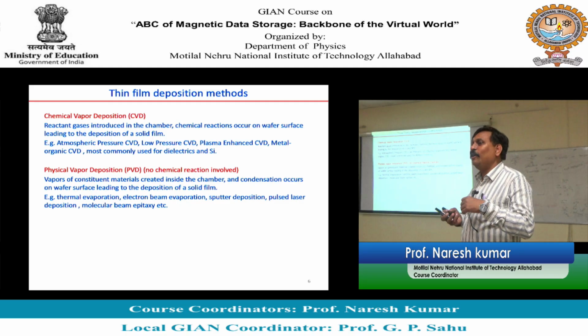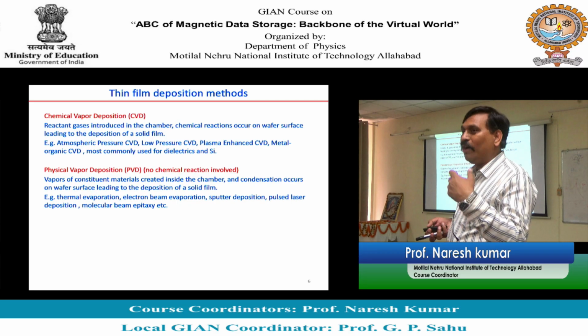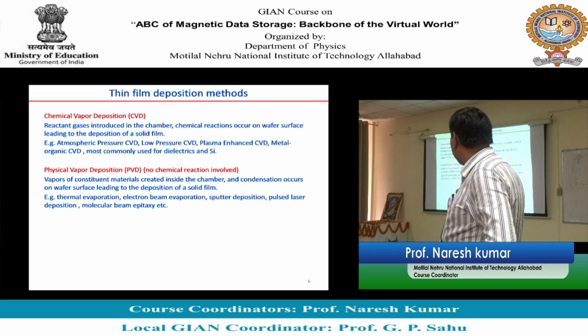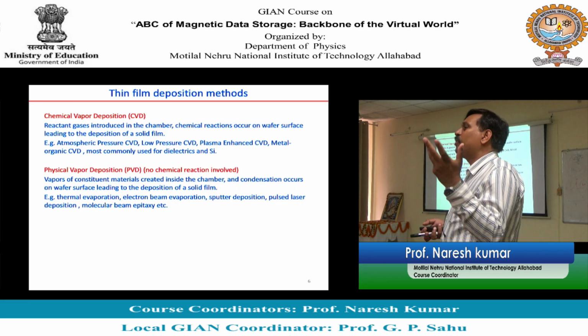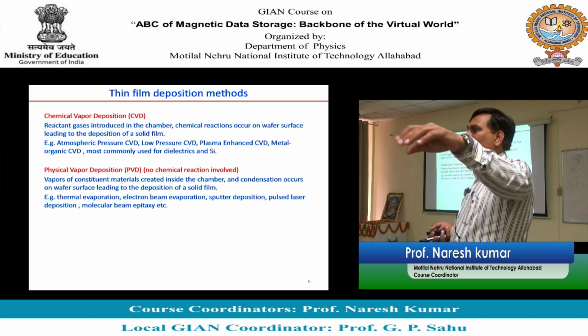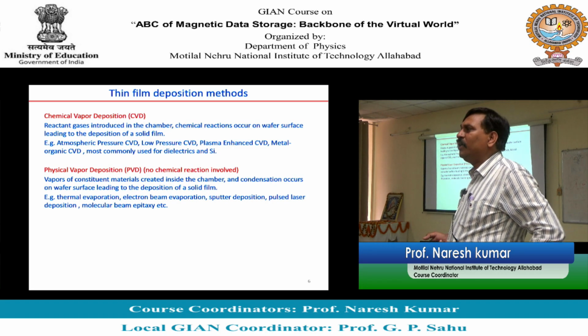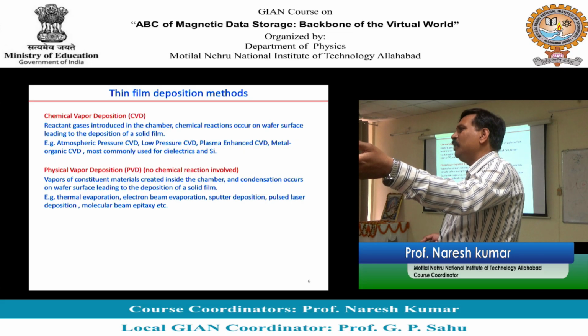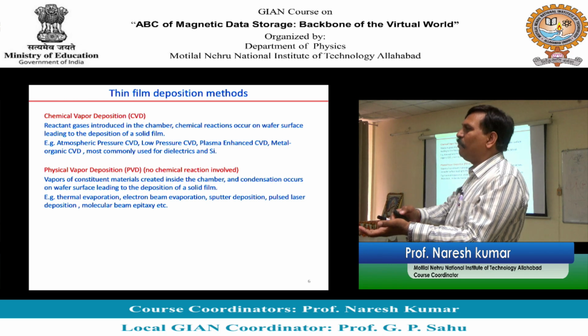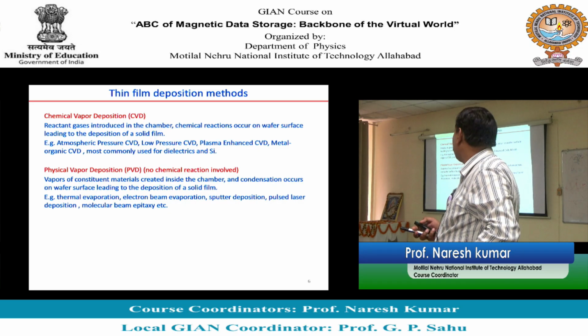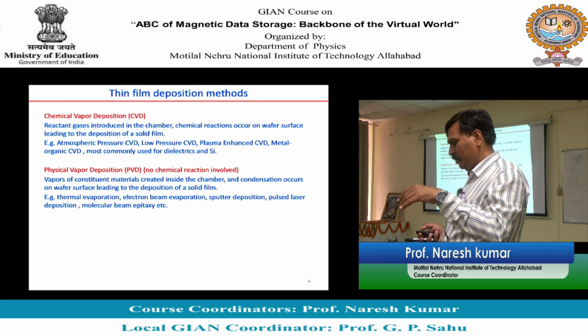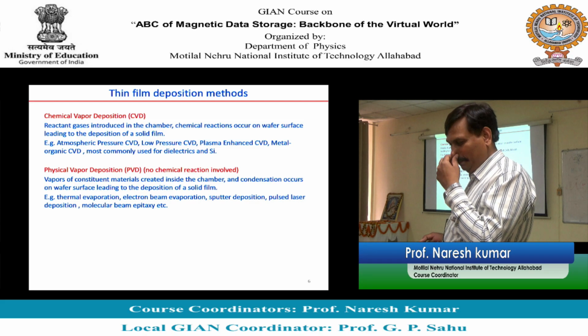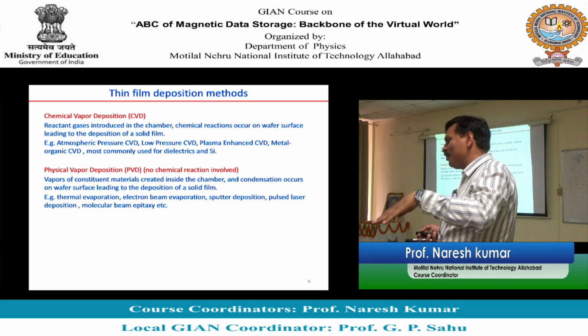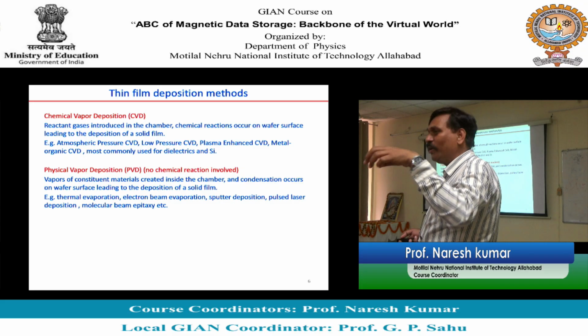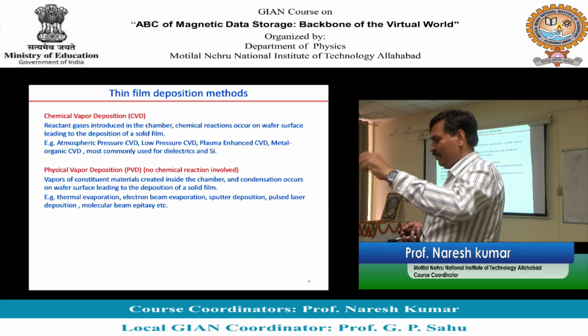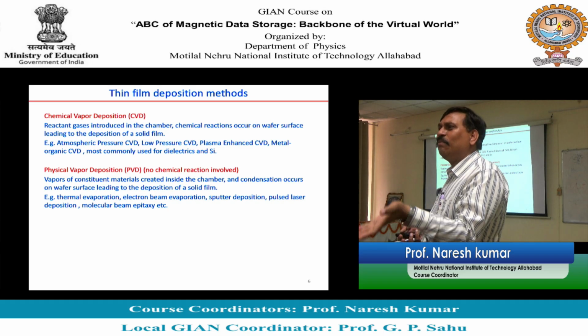Depending upon the kind of resources you have and the kind of requirement you need, you may choose any of them. Suppose you want to make an electrode for some device, electrode means some metal you want to deposit. So this is good for thermal evaporation: you can take copper, aluminum, platinum, right? Put it in a boat, apply heat. It will evaporate the material, and it will be deposited at the substrate. For a device you make contacts. For making contacts you make a mask. So you take a mask of appropriate dimension and place it just next to the substrate.